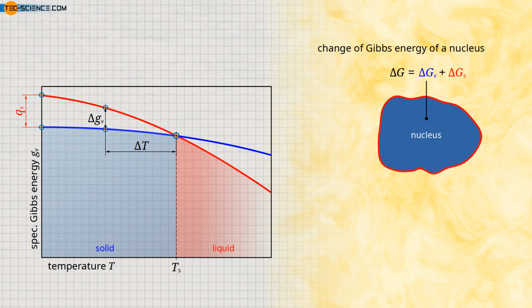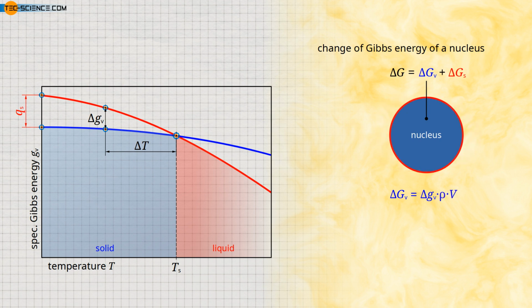Only under the assumption that a solid nucleus forms above the solidification temperature due to statistical fluctuations would this term be positive. This is because above the solidification point, the solid state has a higher Gibbs energy than the liquid phase. Such a situation will be discussed in more detail later. The considered term delta GV can be determined by the specific Gibbs energy and the corresponding mass of the momentarily solidified nucleus. We can determine the mass of the nucleus from the product of density and nucleus volume. For the sake of simplicity, a spherical nucleus is assumed in the following. In this case, the volume of the solid nucleus corresponds to a spherical volume with 4/3 pi times r to the power of 3. It can thus be seen at first that the change in Gibbs energy is proportional to the third power of the nucleus radius.